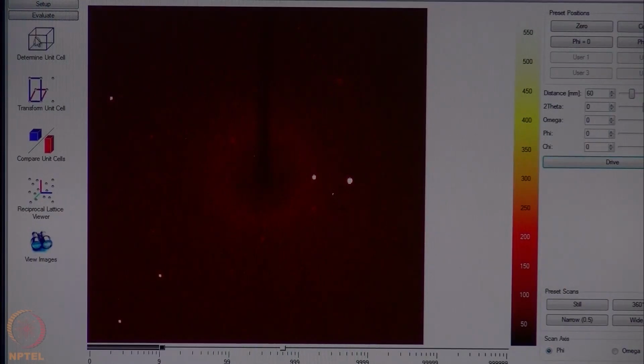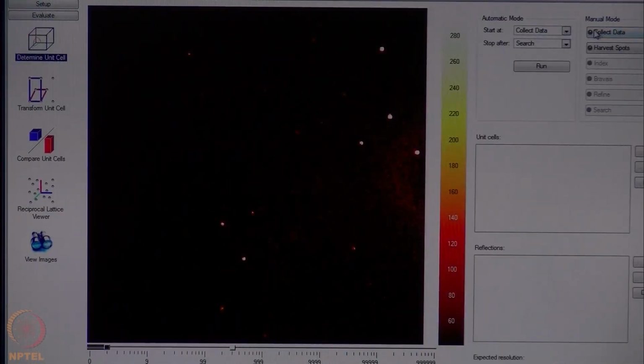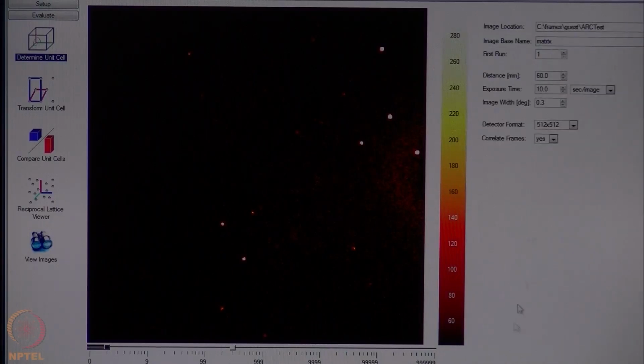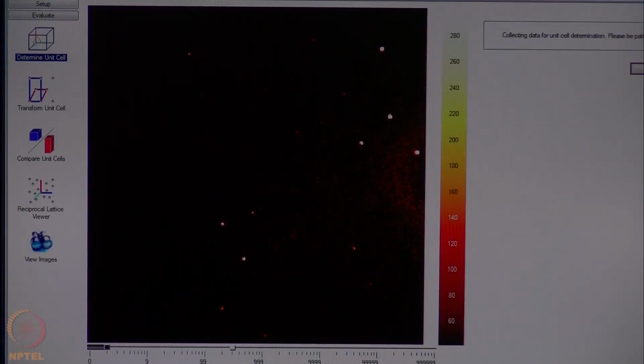So we should go to evaluate, determine the unit cell, and then click on collect data, and then record these images. So there will be 3 sets of 20 frames recorded with 10-second exposure each, which would take about 12 to 13 minutes to record.